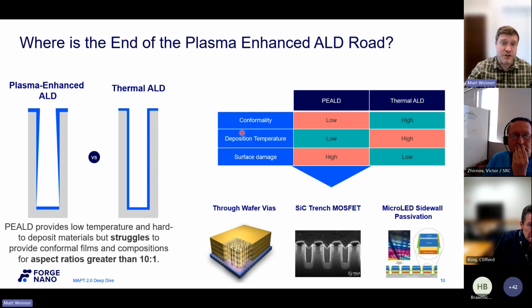Of course, with deposition temperature, you can really reduce your deposition temperature with plasma. Right, you're putting more energy in through a different mechanism. But with thermal ALD, to sometimes get that same quality of film, you need a higher temperature. But here's another trade-off. You can damage the incoming surface with plasma, right? That's well known. So you have to be very careful how you start your ALD growth, especially since it's so thin per cycle, right? And I'll talk a little bit more about that on the left side here. But with thermal ALD, the chances of that are pretty much zero.